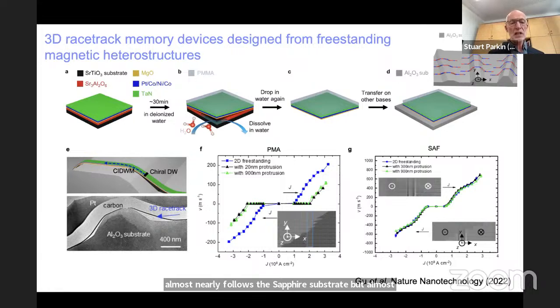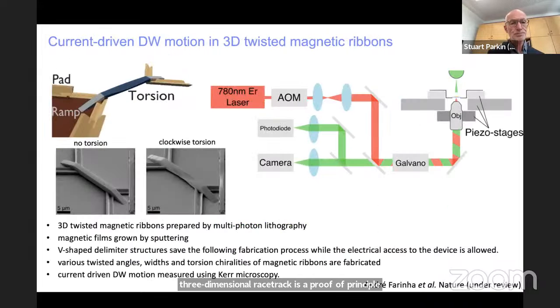And we can then pass domain walls into this racetrack. And what Kei-Gu found was that if you take the SAF racetrack on the right-hand side, you can see the similar velocity versus current density. This is the current density in nanosecond long pulses as the domain wall is moved over these protrusions up to nearly 1 micron tall. So this is amazing. Here they're moving at speeds of nearly 700 meters per second, so very fast. And this is then, if you like, the first three-dimensional racetrack. It's a proof of principle that we could build a three-dimensional racetrack in this way.